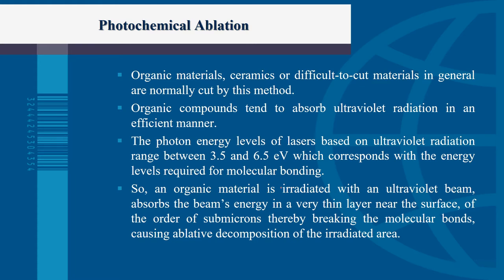So if an organic material is irradiated with an ultraviolet beam, it absorbs the beam's energy in a very thin layer near the surface, on the order of submicrons, thereby breaking the molecular bonds, causing ablative decomposition of the irradiated area. So for example, certain ceramic materials are very difficult and require high energy to cut through with a laser. What we do is that the laser itself will just irradiate the surface and slowly break down the material layer by layer.